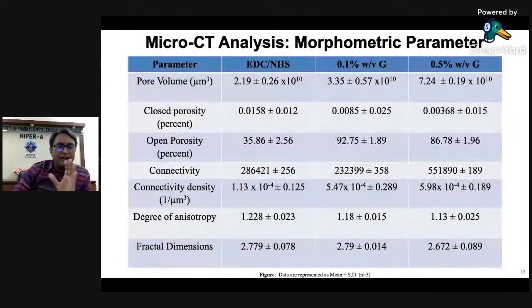We have done some more microCT analysis and found important figures. For example, the closed porosity is much less in 0.5% graphene compared to EDC-NHS. Likewise, the open porosity is much more in graphene incorporated cryogels compared to only EDC-NHS collagen cryogels. Connectivity is also high, and the degree of anisotropy is quite low, making it a more stable structure. So overall, in terms of porosity and interconnectivity, the graphene incorporated cryogels have shown better porous morphology compared to EDC and NHS cross-linked collagen.